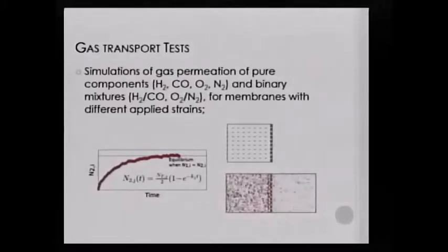After a while, upon the system being equilibrated, we release this barrier, and we allow gas flow from one side to the other, as you can see here. And we use the amount of molecules that cross this barrier as a measure of gas flow, which we use to measure the rate of transfer from one side to the other.